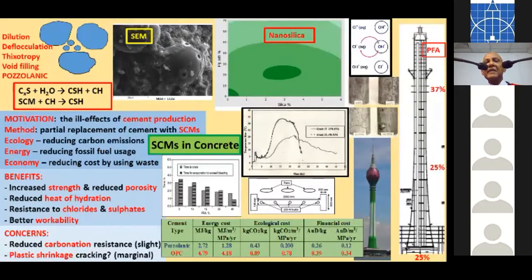And fly ash is made of spherical particles like this. Their shape is spherical. So this is a scanning electron microscope image. Now a cement particle is about 100 microns wide, maybe about 1/10 of a millimeter. But these fly ash particles are much smaller and spherical like this. So there are 3 or 4 things that happen when you mix this fly ash with this cement. For one thing, there is dilution. There are various things that cement particles do that are not always beneficial. For example, it emits a lot of heat during hydration. And there are various reactions that are not very attractive in cement. For example, it is susceptible to chloride intrusion and also to sulfate attack. So those effects are diluted by including this supplementary cementitious material.